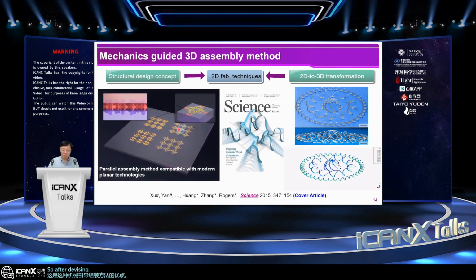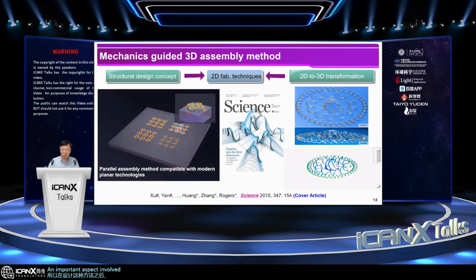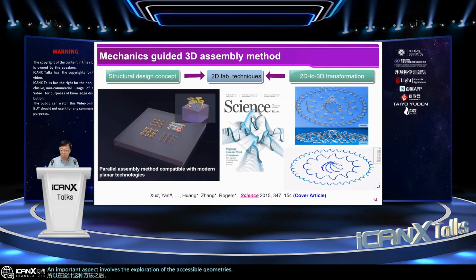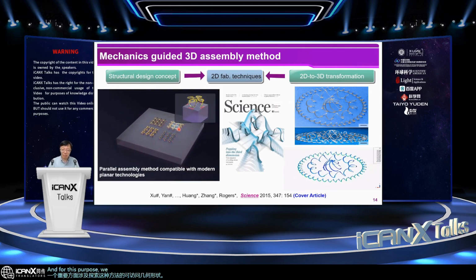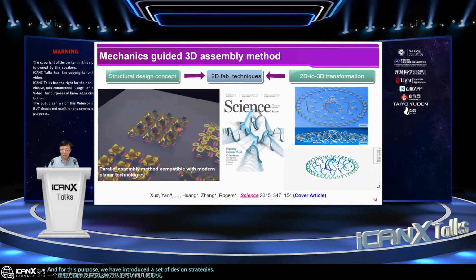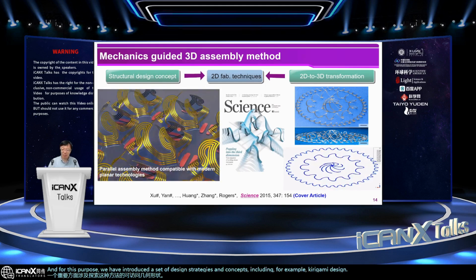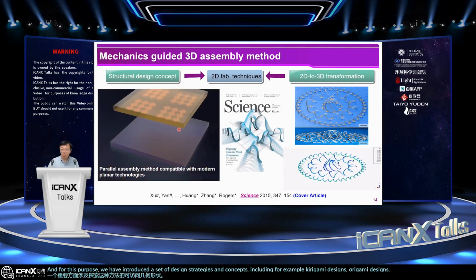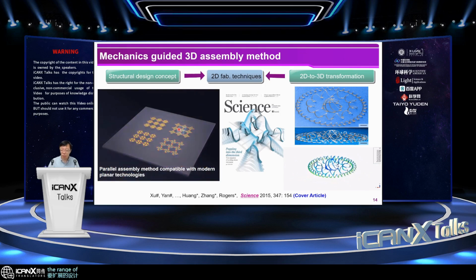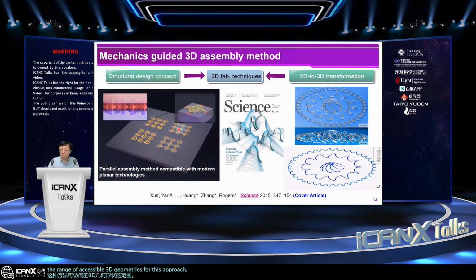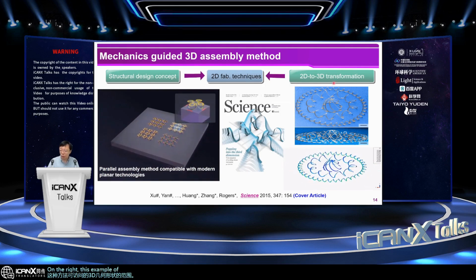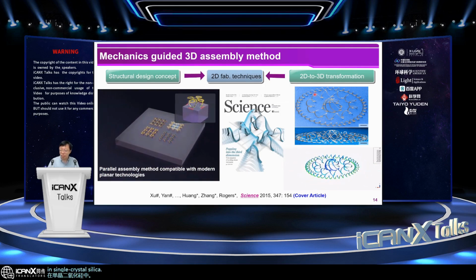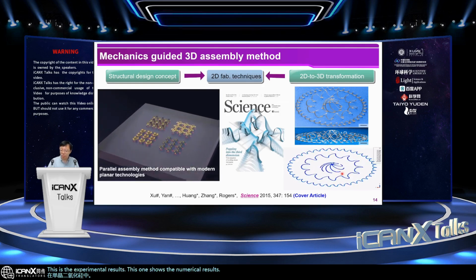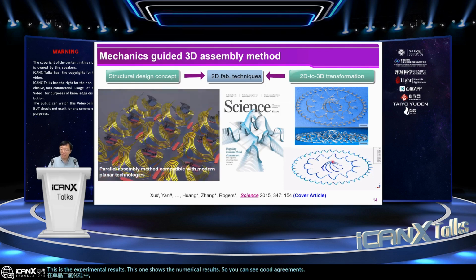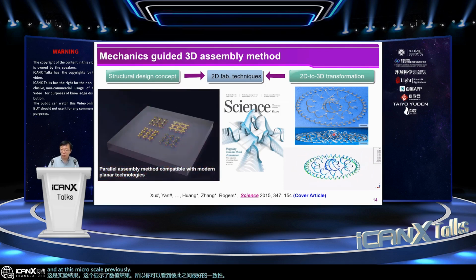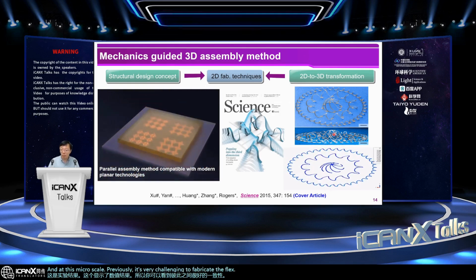So after devising this approach, an important aspect involves the exploration of the accessible geometries for this approach. And for this purpose, we have introduced a set of design strategies and concepts, including, for example, origami designs, multi-layer and interlocking designs, to expand the range of accessible 3D geometries for this approach. On the right, this is an example of a tri-layer toroid in single crystal silicon. This is the experimental result. This one shows the numerical result. So you can see good agreement between the two. And at this microscale, previously it was very challenging to fabricate flexible three-dimensional silicon structures.